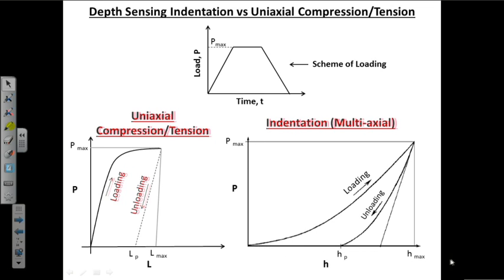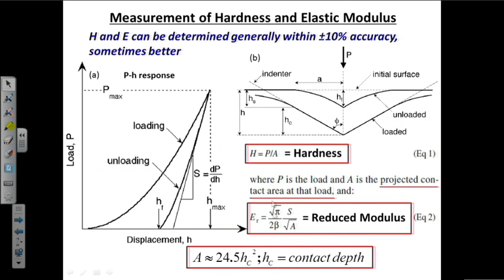In indentation we obtain a load displacement graph which looks something like this, where with increasing load, the depth of penetration increases, and you can see at a certain point the slope of the P-h graph changes, and this region marks the elastic to plastic transition. Now if we increase the load until P max and then unload the material, the material follows this kind of unloading path. Once we know that, we can use this P-h graph to measure the hardness and elastic modulus of a material. It turns out that the hardness and elastic modulus can be determined within plus minus 10% accuracy and sometimes better.